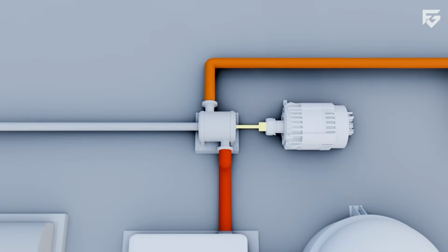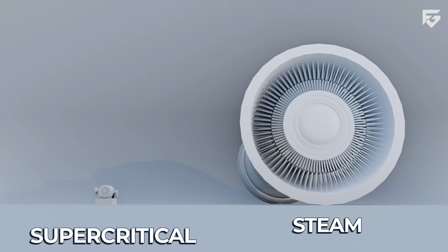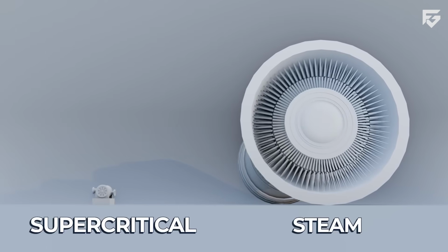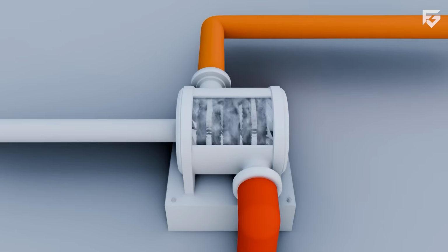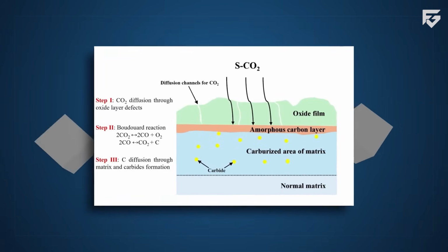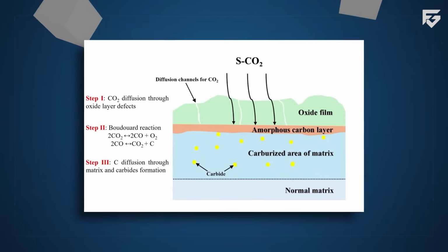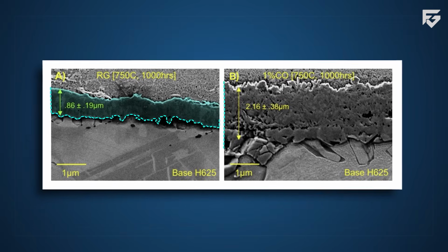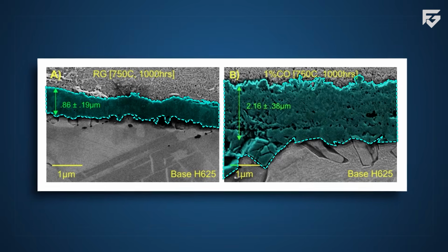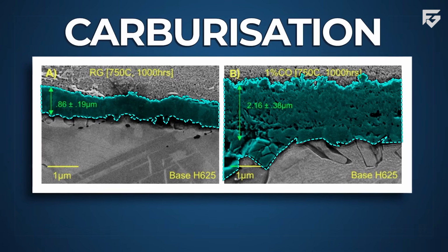creep and material failure. However, supercritical CO2 introduces another problem called carburization. At high temperatures, carbon atoms can slowly diffuse into the metal structure. This forms brittle carbide compounds along the grain boundaries of the alloy. Over time, the metal becomes weaker and more prone to cracking.